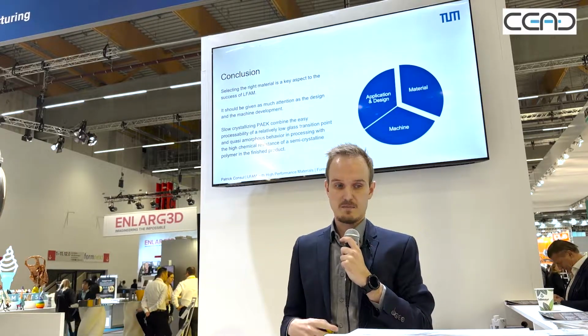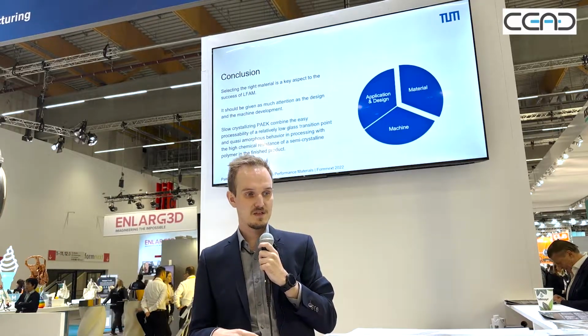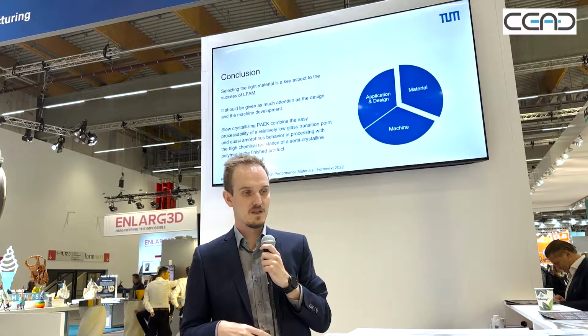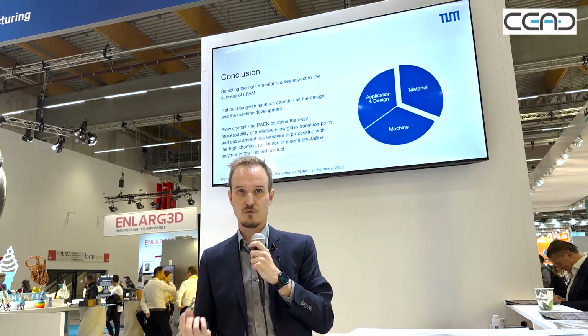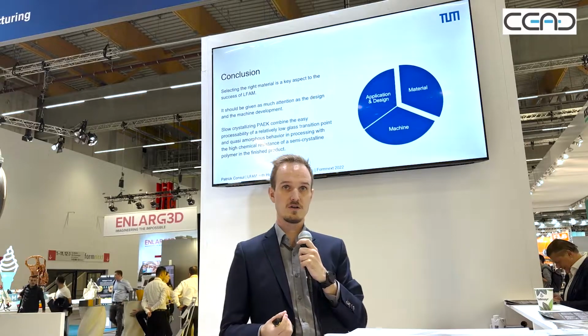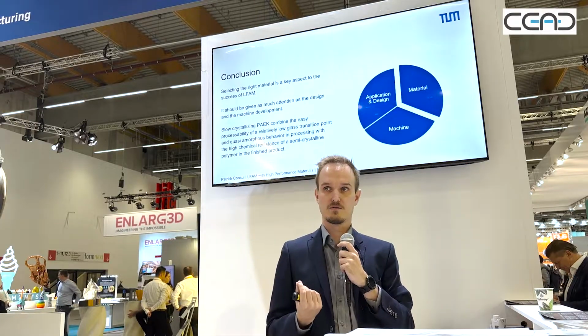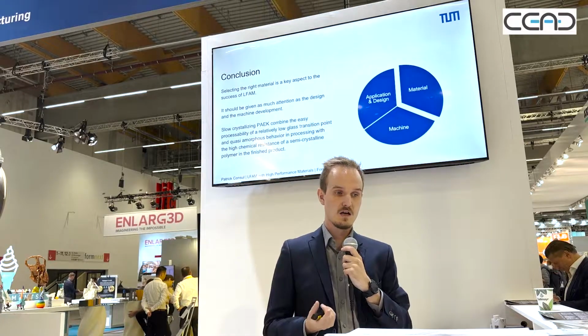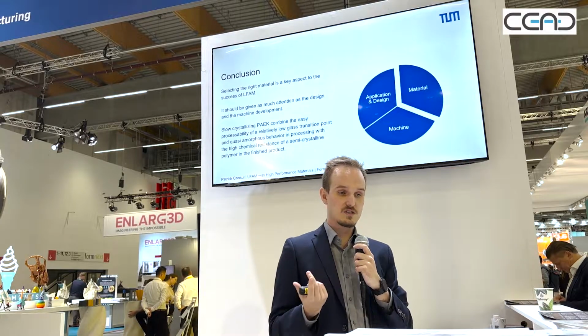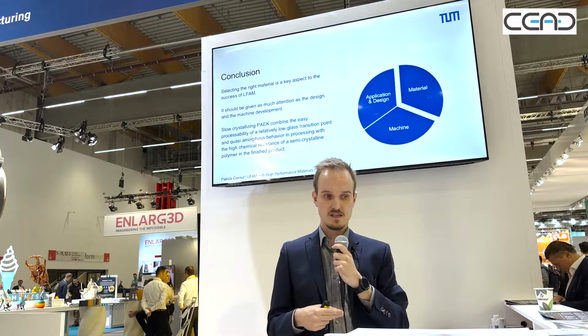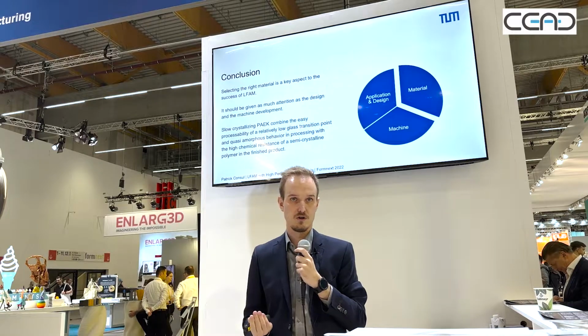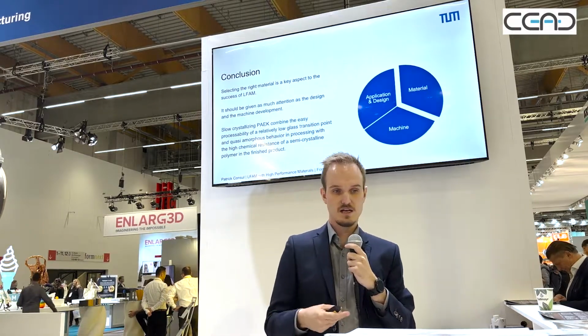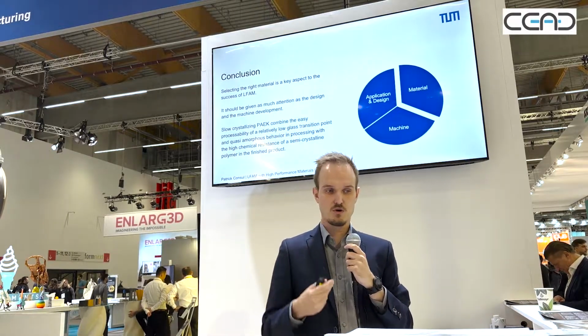And yeah, the big benefit of this slow crystallizing PAEK is that it kind of combines the best of both worlds. In the finished product, you'll have the high chemical resistance of a PAEK because it's crystalline, but during processing it behaves like an amorphous polymer with good bonding and actually also a little less warping.